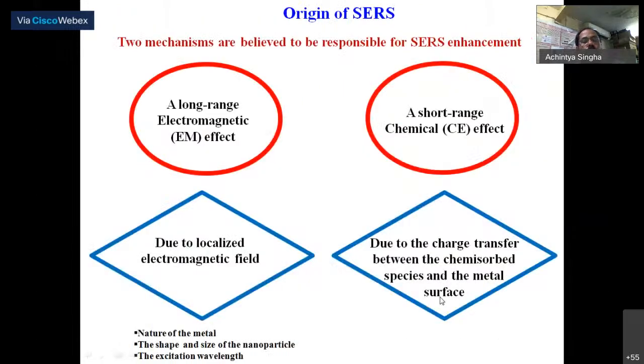The electromagnetic effect is the long-range effect, and the major enhancement is due to the electromagnetic effect, the localized electromagnetic field on the metal surface. The other is the chemical effect. The chemical effect is due to the charge transfer between the molecule and the metal surface. So one enhancement is due to the localized electromagnetic field on the surface of the metal particle, and the other is the charge transfer between the metal and the molecule.